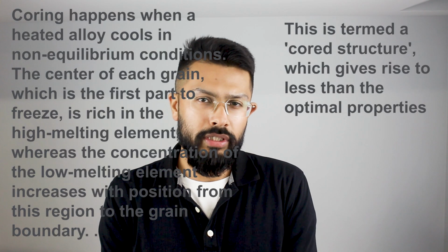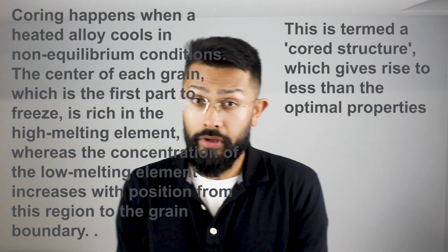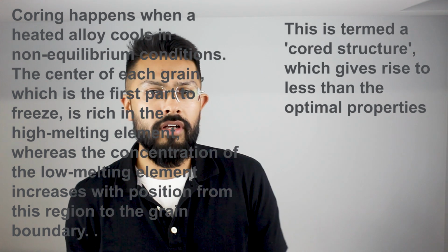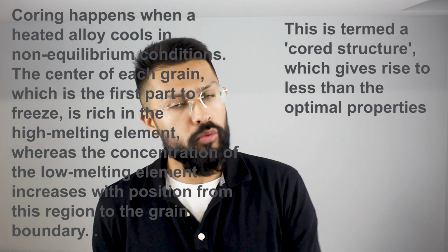The casting is then cleaned, and when platinum or palladium are present, a homogenization heat treatment may be carried out to remove coring. This involves heating to 700 degrees for 10 minutes and then quenching. The casting is then polished and its fit in the mouth is checked. Any minor adjustments such as bending of clasps, etc. are made at this stage while the alloy is still in the softened state. If adjustments are made, a low temperature stress relief anneal should be carried out.